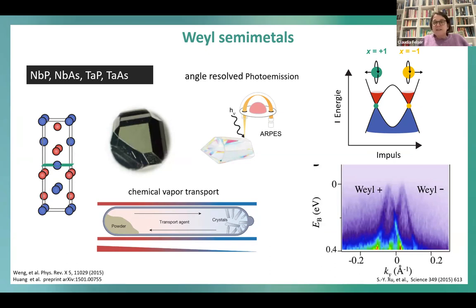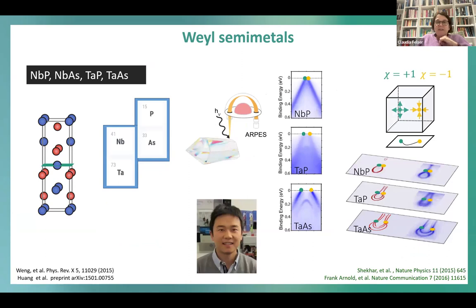And on the right side, you see on the upper part, my scheme, which I always showed you. But on the lower part, you see really photo emission. It's like a photograph of the electronic structure. And you see nicely how similar it looks. If you do a photo emission, you really see the linear dispersion. And you see that the bands are crossing at the top. And on the next slide, we probably see the surface state.